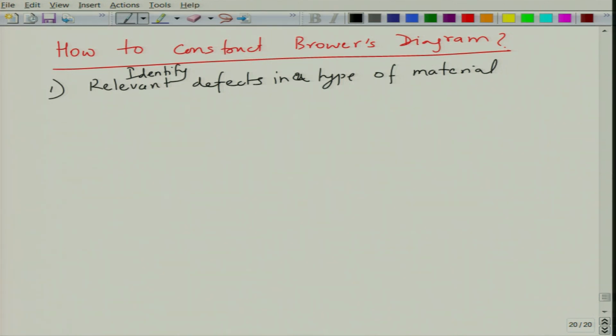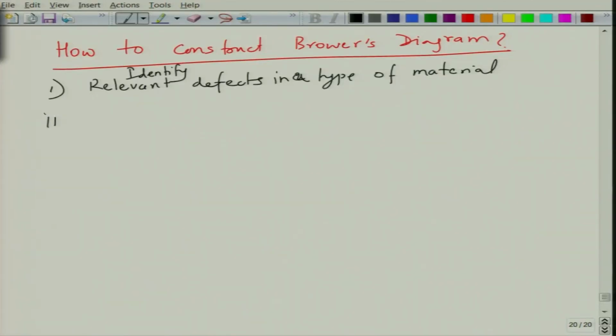Okay. Generally, for a close packed structure, one can neglect interstitials. If the structure is very heavily close packed, then interstitials are not possible, because the interstices are smaller, and generally oxygen interstitials are bigger. As a result, anti-Frenkels will not be possible. So, for close packed structured materials, you will mainly consider what we call Schottky disorder, not anti-Frenkel or Frenkel disorder. That judgment has to be made by you as a scientist, and once you identify the defects and type of defects, intrinsic defects, etc., you write the defect reactions.